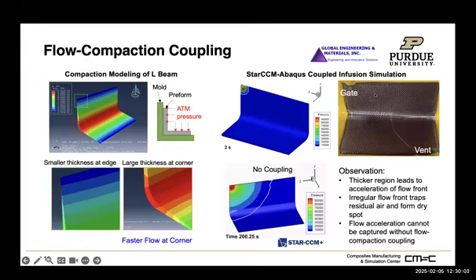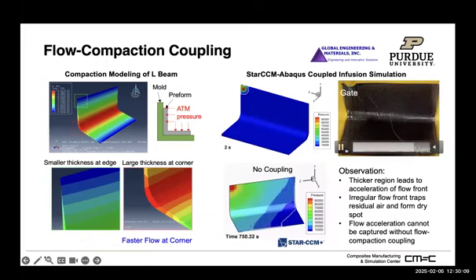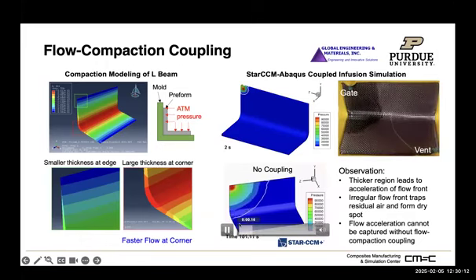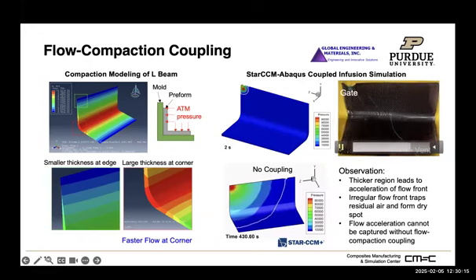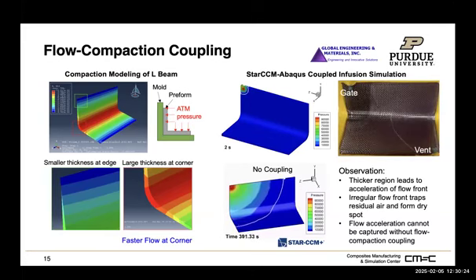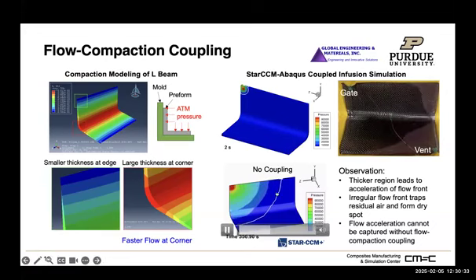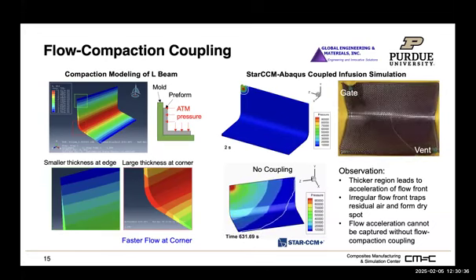But unfortunately, this is not what we observe most of the time in the lab. If you look at this movie more closely and compare it with the ideal simulation case, the main difference is that we see an acceleration of the resin flow front at the corner. This is pretty common; we have seen it multiple times. So when we go back to our simulation, we know that simply assuming a porous medium with some permeability to simulate the resin flow front is not sufficient. One of the phenomena behind it is the compaction force. The compaction will affect the permeability as well.